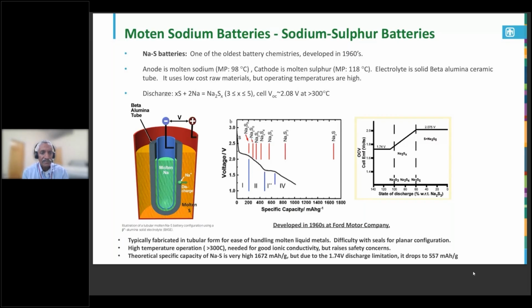In the reaction, when you discharge this battery, first you form sodium pentasulfide followed by different polysulfides. But if you discharge lower, some of these polysulfides are not really reversible. For that reason, they discharge it only up to 1.74 volts, and then they cycle it between 1.74 and the open circuit voltage 2.08. Because of that, it loses some capacity, but still these are pretty good batteries. Go to the next one, in a commercial stage.